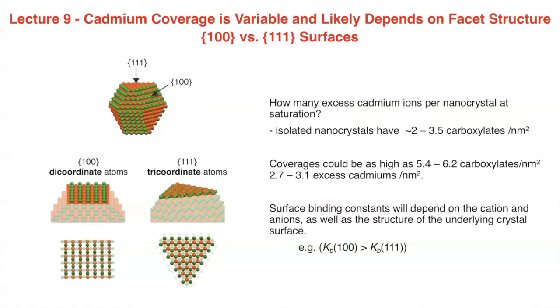So a huge range, and in most crystals of this type, the atoms on their surfaces show a lot of dangling bond character. There's nowhere near coordinative saturation of the atoms on the underlying surface, which is really interesting from a coordination chemistry perspective, to have lots of vacancies and open coordination sites. And it turns out that they can't be accessed for steric reasons.